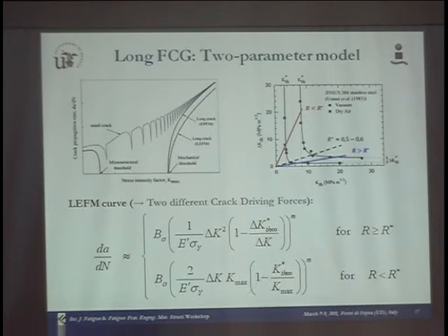When we go to vacuum, we have a continuous change, even at crack growth rates down to 1/10, 1/100 of one lattice spacing. So we compare completely different things, and one has to be careful when one draws such diagrams. That's only my comment.